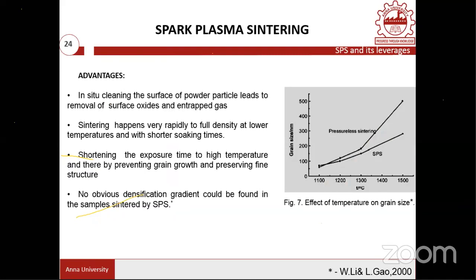The advantage of this spark plasma sintering is that full density, close to full densification, can be achieved, and the materials are exposed for a shorter time, which prevents grain growth, and there is no obvious densification gradient. So the density would be the same at the outer surface as well as the inner surface. Here it is compared with pressureless sintering: in SPS, the grain size is retained. Even if there is some grain growth, it is not tremendous,